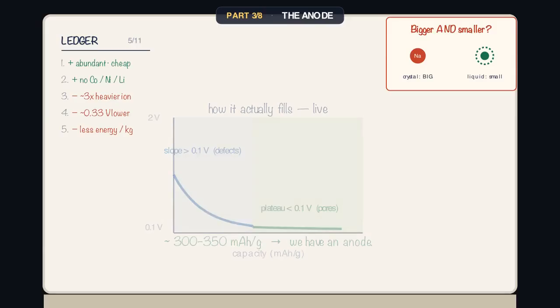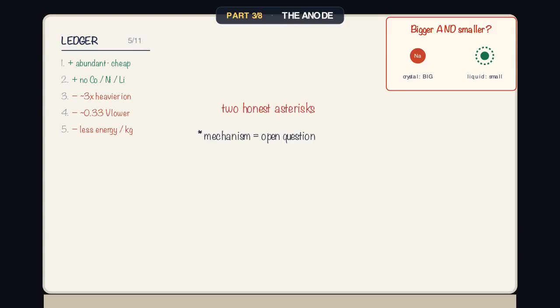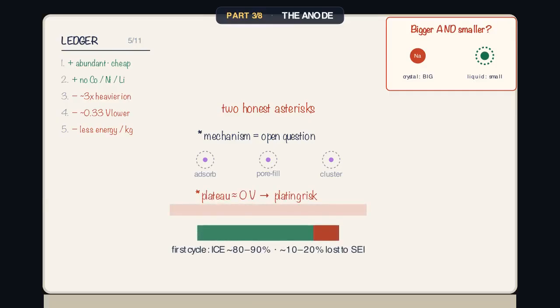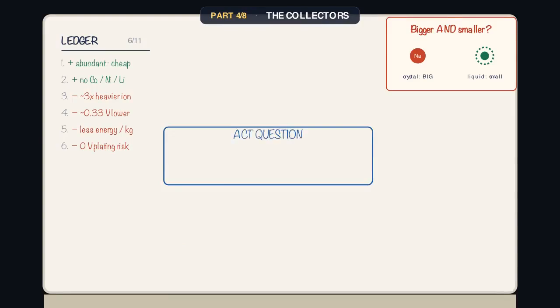We have an anode. 2 honest asterisks. 1. Exactly how hard carbon stores sodium, adsorption, pore filling, clustering, is still genuinely argued in the literature. Competing models, unsettled. Don't let anyone tell you it's solved. 2. That plateau sits a hair above 0 volts, so charge too fast or too cold, and sodium plates out as metal on the surface, the same danger that haunts lithium. And the first cycle permanently swallows 10 to 20% of your sodium, building a coating. Nothing here is free. Act 2 question, keep it open.